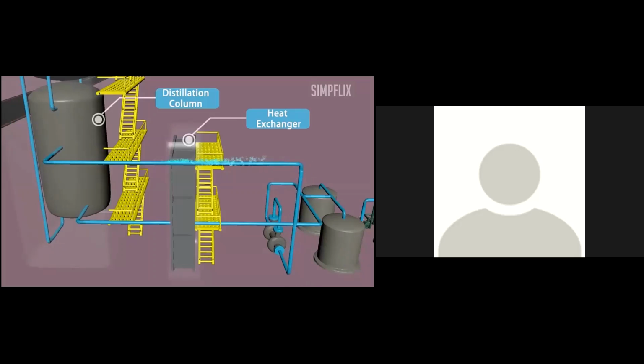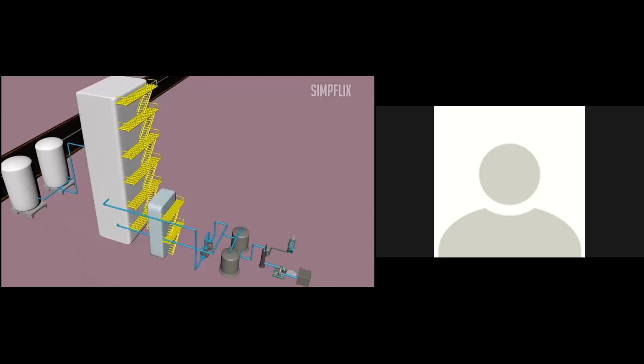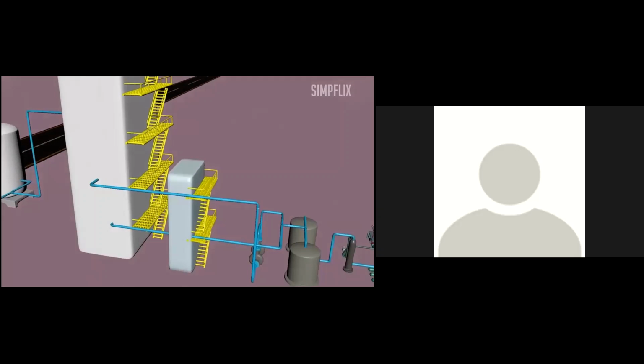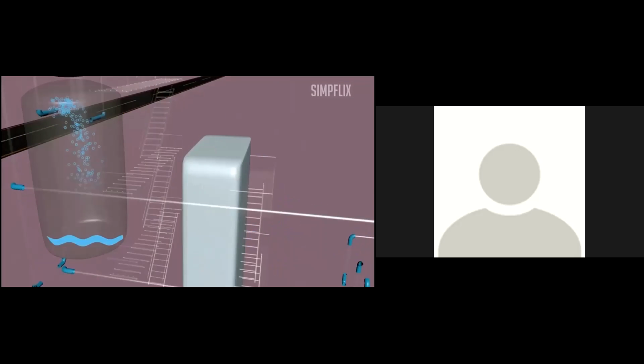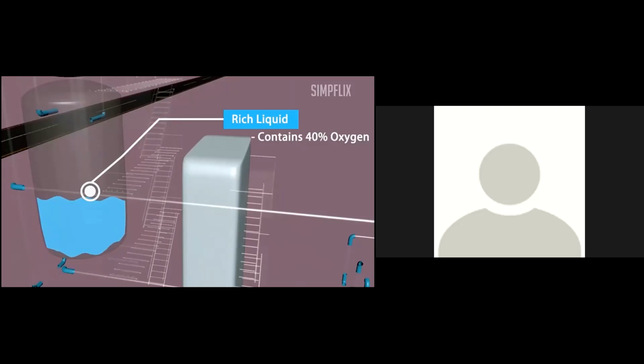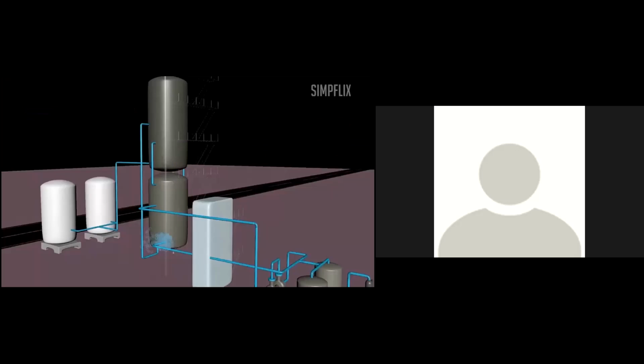Cold air goes through the heat exchanger and fractional distillation column. Air temperature is -165 degrees Celsius. At this temperature, air inside the fractional column will get liquefied, and this liquefied air is having 40% content as oxygen. This liquid is called rich liquid, as oxygen is taken and given as reflux at the middle of fractional distillation column.